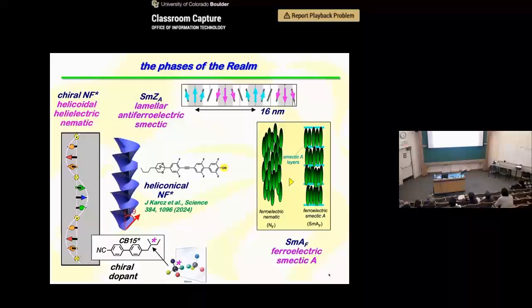Okay, so then this extra phase in DIO is actually a lamellar phase. So you imagine in three dimensions sheets. So this is a stacking of sheets. In this sheet, the polarization is up, and in the neighboring sheet, the polarization's down. So this is an antiferroelectric phase. So you have domain walls here where the polarization is pointing up, and then there's a nematic layer nanometers thick and then pointing down. Okay, that's the smectic ZA phase.